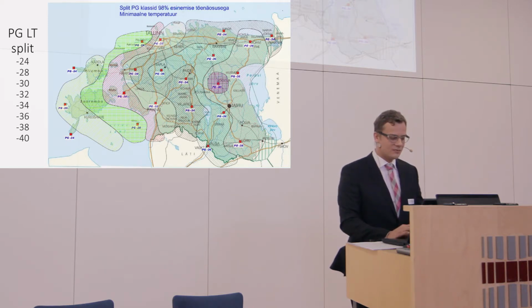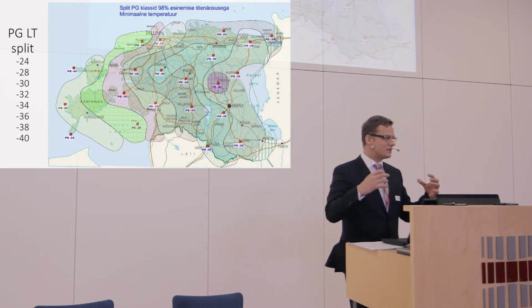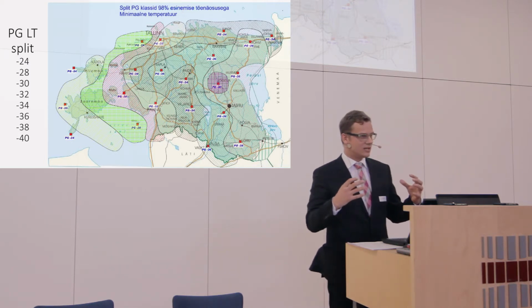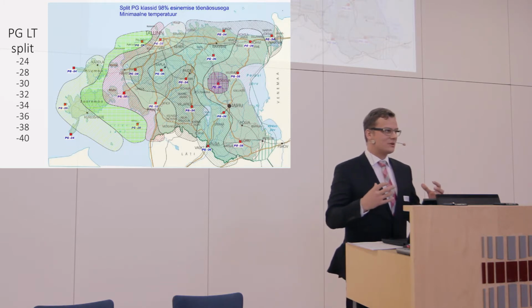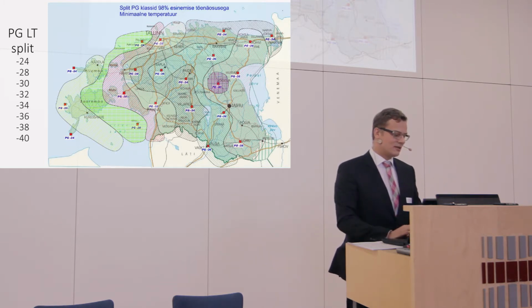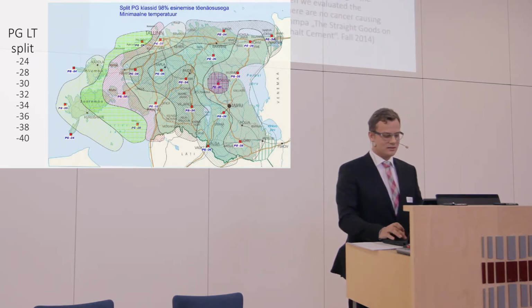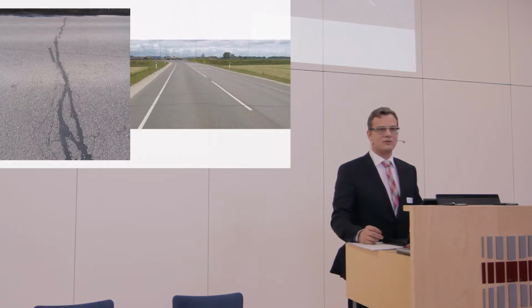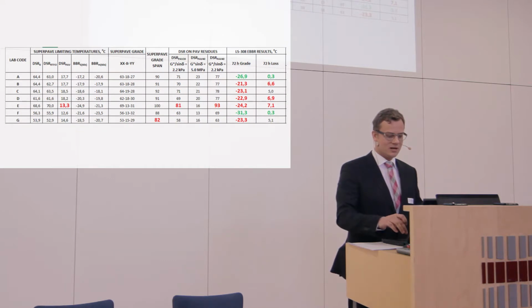So for sure, when you use this bitumen here, you are confident that it will withstand minus 30 degrees, but in reality, when there's physical hardening going on, the minus 30 shifts to minus 24 degrees, and as a result, you can see a lot of cracks on your roads. So that is the physical hardening.